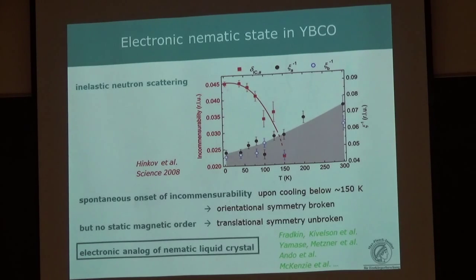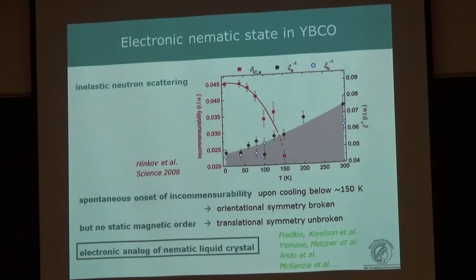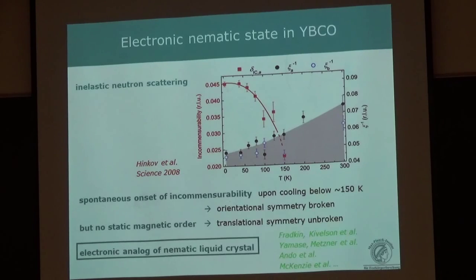In response to a question about the incommensurability as a function of doping: it's zero in the undoped antiferromagnet, and then increases with doping. Looking at the wave vector as pi ± δ (or pi ± δ, pi ± δ), this delta increases with doping. The doping dependence is roughly similar to the lanthanum strontium copper oxide family, except that in LSCO at low doping the spin correlation modulation is both along x and y, while here in YBCO it's uniaxial.